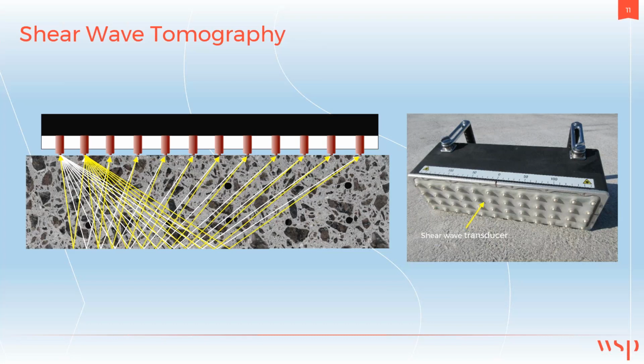This particular tomography method employs an array of transducers oriented such that as one transducer imparts a signal, all of the other transducers are in a listening mode and receive response from the signal. So the schematic on the left is showing, for example, that the white lines are the signal from the first array element reflecting to all the other array elements and getting a response.